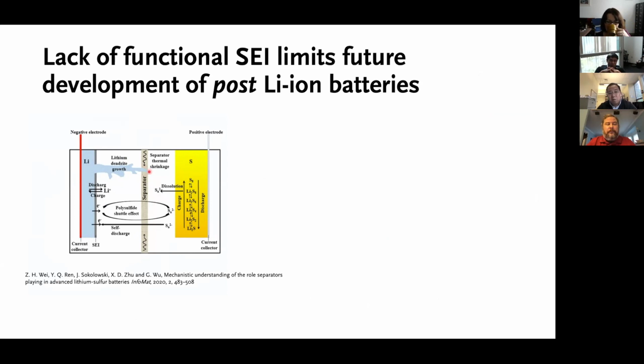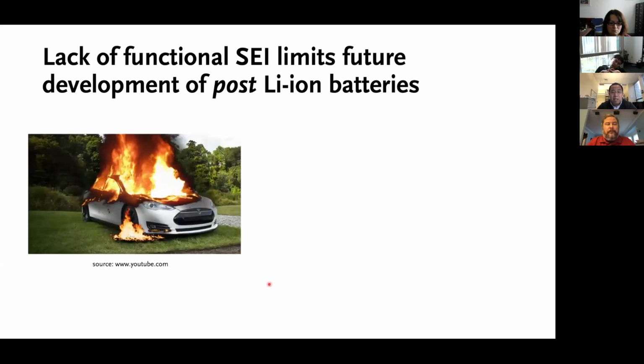It also has a result of the intrinsic properties of lithium. But to make the long story short, when you have this dendrite growth, it could really grow into an arc. It's like a lightning arc. It can penetrate the separator and short the anode and the cathode. And that's when you may have a spectacular failure. And this is a huge problem, particularly for public perception. So as you can see, the SEI is the key, is really the last stand that prevents this from happening.